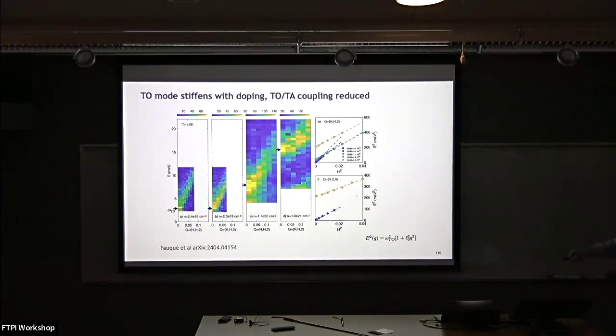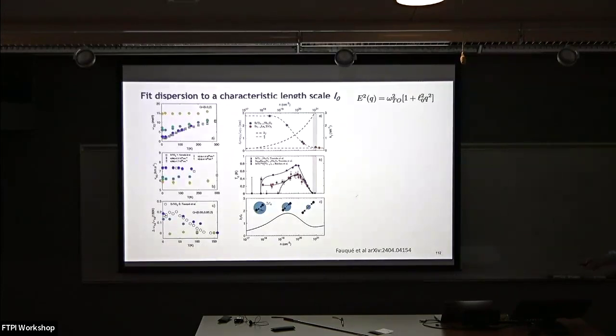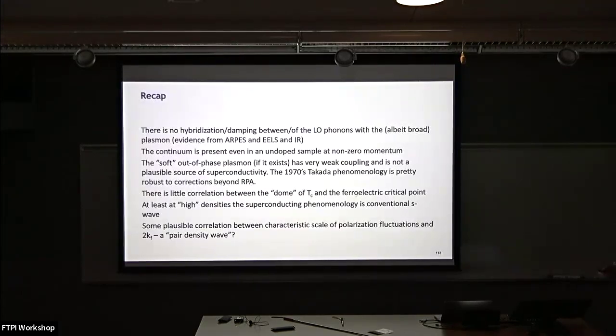This is a very recent paper from Fauqué. Just to close with his punchline: he can extract a length scale from this function. That length scale, which I'm plotting here, changes as a function of carrier density, and he would like to argue that the peak in Tc happens when 2k_F L is below 1. This is just an observation. I don't think there's any theory behind it, but I want to ask Steve about this. Okay, so there's my close, and we can discuss.